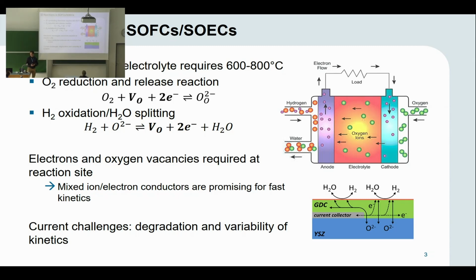As a quick introduction, a solid oxide fuel cell is a high-temperature electrochemical device with an oxygen ion-conducting solid electrolyte. And this requires a relatively high temperature for sufficient oxygen ion conductivity. So we investigate our samples at 600 to 800 degrees. And the most important reactions that we investigate are the oxygen reduction reaction in oxygen atmosphere and the hydrogen oxidation or water splitting reaction at the anode side of the solid oxide fuel cells.